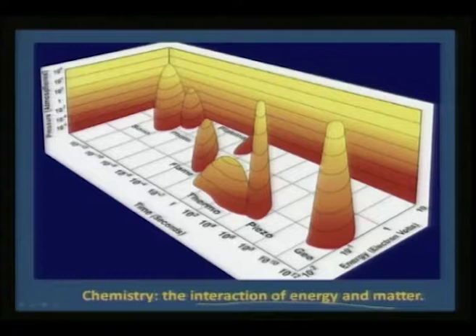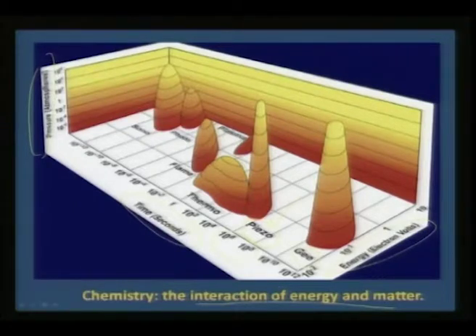We are talking about photochemistry in this time scale. We are talking about energy, time, and pressure. If you think of pressure induced reactions, then the one which stands foremost is piezoelectric synthesis, in which case you achieve very high pressures, but this happens in a time scale of 10 power 6 to 10 power 8, which is a very slow process. Then you have geothermal synthesis, which is also very slow, of the order of 10 power 10 to 10 power 12 seconds. But all these fall in the same energy scale, 10 power minus 1 eV, and that also includes flame chemistry to some extent.